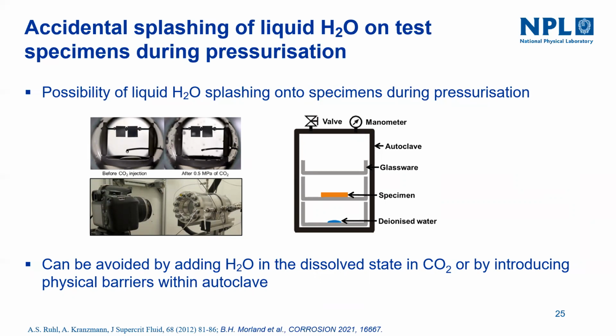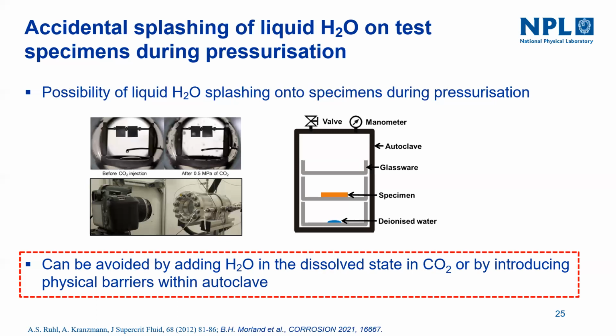Most of the corrosion studies have been done in a closed system where the occurrence of splashing is unknown. How it can be avoided is, one, by adding water in the dissolved state, or by introducing physical barriers such as this one. But we need to take care if we introduce any flow over the specimens.